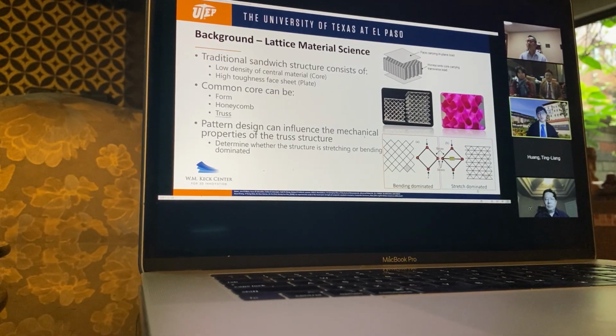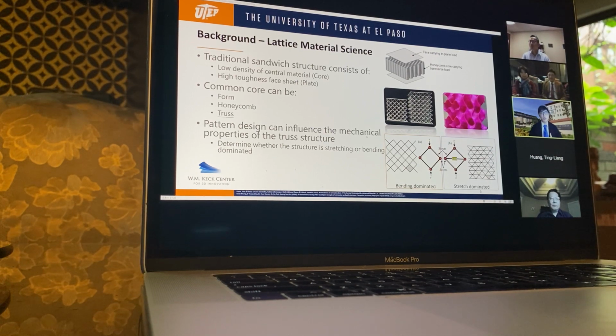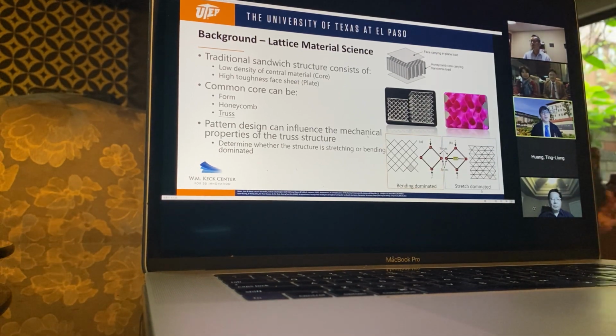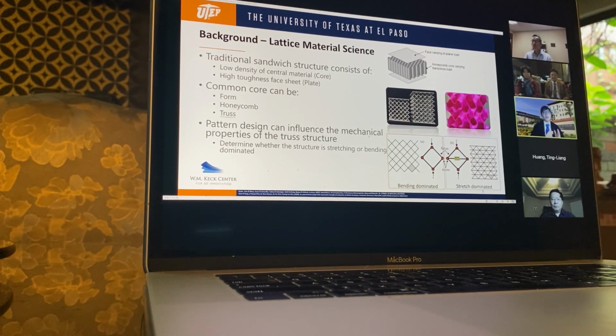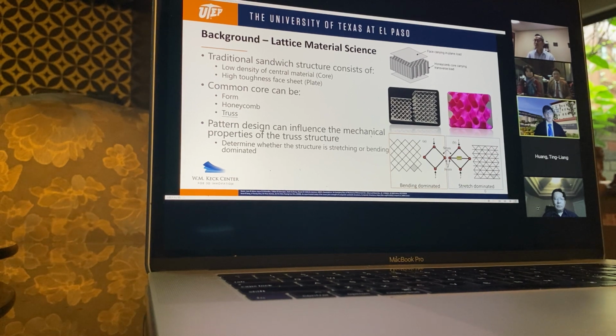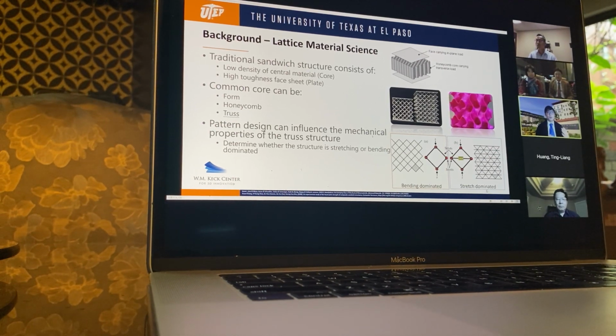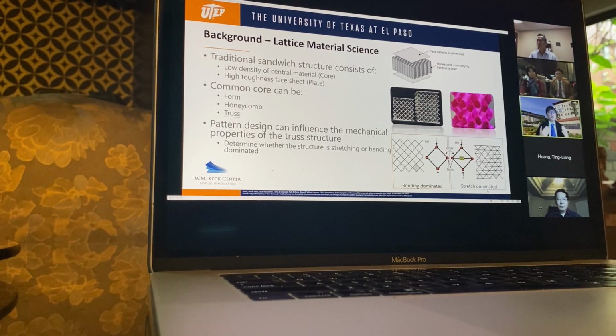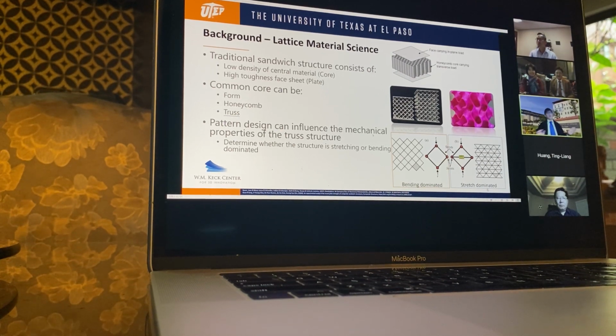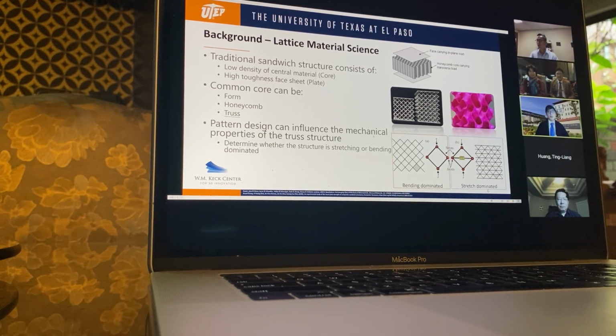If the joint connects with 6 struts, it's stretch dominant because there is one strut in the middle of the pattern, so the stress can be uniformly divided around. Because of this mechanism, stretch dominating patterns often have higher strength against deformation. So by this unit cell design, we can use a fundamental arrangement to design a soft unit cell and a hard unit cell with a stretch dominating arrangement.